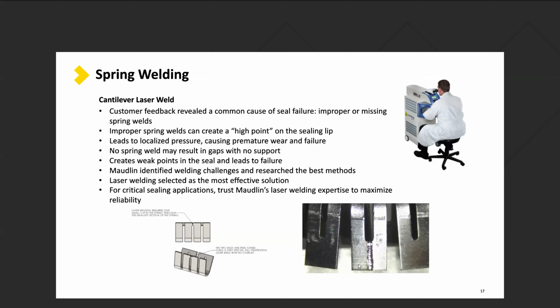And we pull test this. The base material usually stretches and yields before the weld breaks, so the welds are very, very strong. That sometimes comes up as a concern, but that weld is stronger than the base material in most cases. For critical applications, there's no other way to do it.